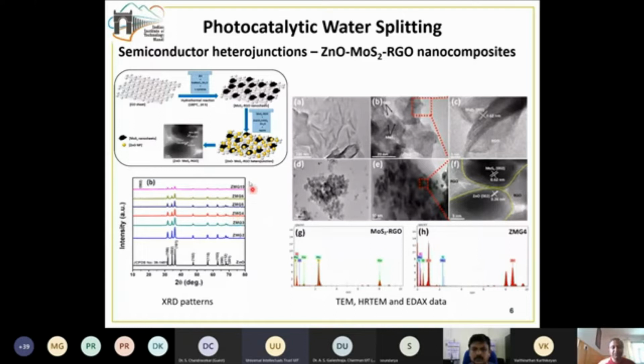In all the cases, since the zinc oxide is the predominant material, we could clearly see the X-ray diffraction pattern of zinc oxide. But we cannot see the MoS2 or the RGO presence from the X-ray diffraction pattern, which we observed through the Raman spectroscopy, which I'll show in the subsequent slide. And at 10 weight percent, we start to see a little bit of the MoS2.